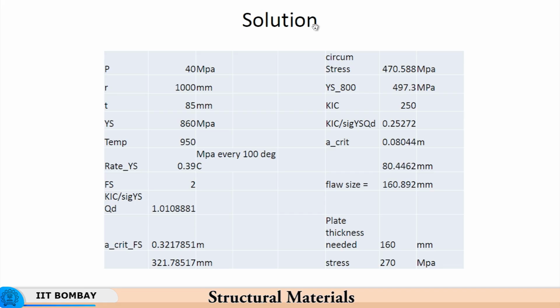So, basically one would be happy that at 270 MPa the material is not going to yield, and it also shows that with 160 millimeter plate thickness, the critical flaw size is slightly greater than the plate thickness. Now, if we take a factor of safety of 2, what happens is the critical flaw size is this much. So, 161 or even higher thickness is okay if you take a factor of safety of 2. So, the stress of 270 MPa is okay for yield limited design, but now if you look at the creep